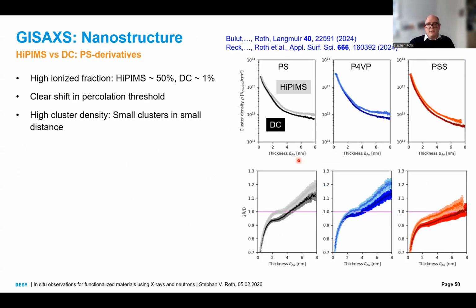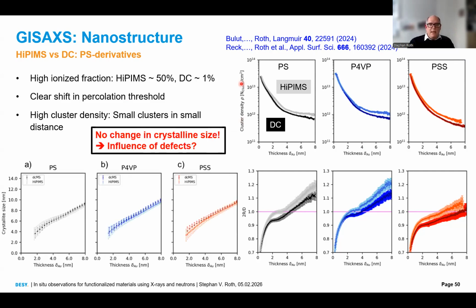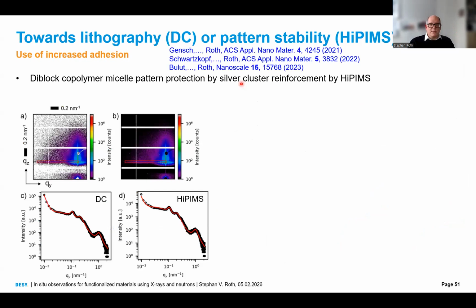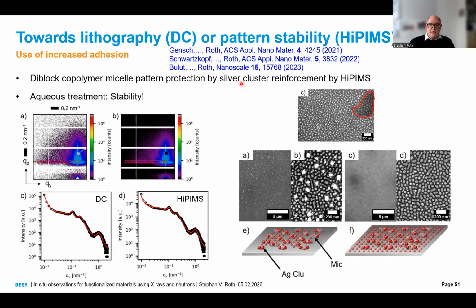And one important point is when we compare this HIPIMS to DC, what we see is that this HIPIMS structure really gives many small clusters in smaller distance. Smaller clusters in smaller distance means higher cluster density, so a more compact layer compared to DC. We can look also into the crystallite structure. We can look into the adhesion.